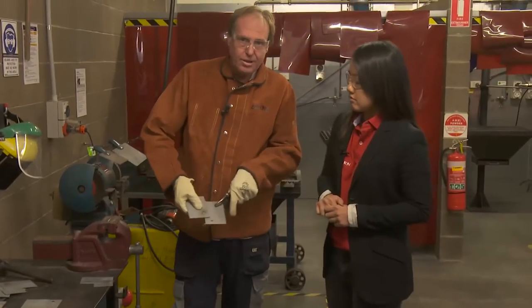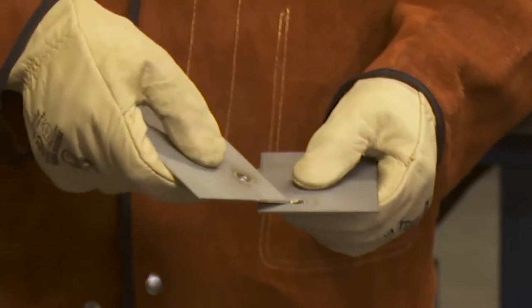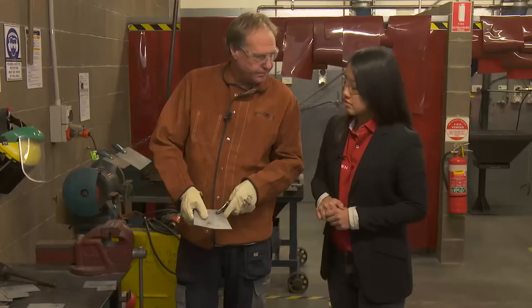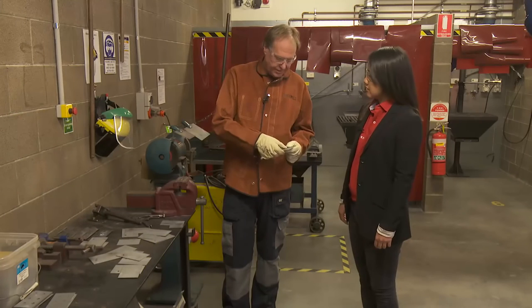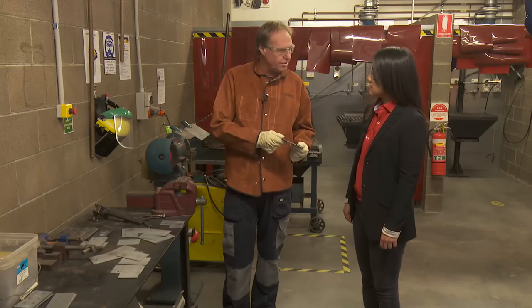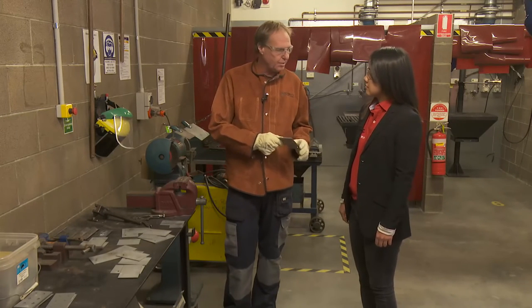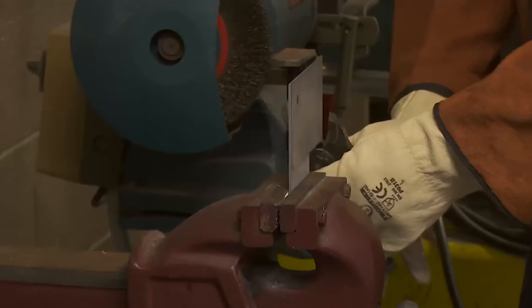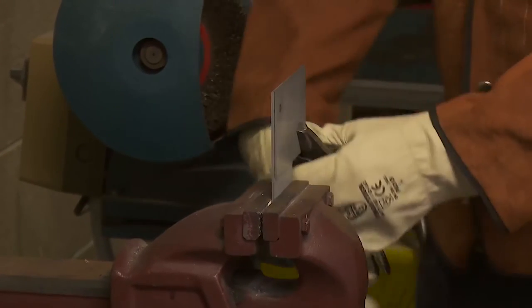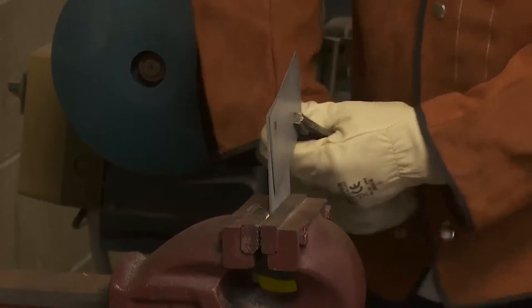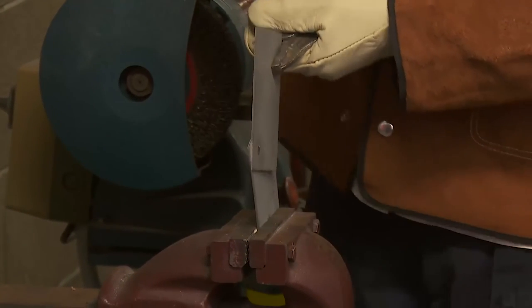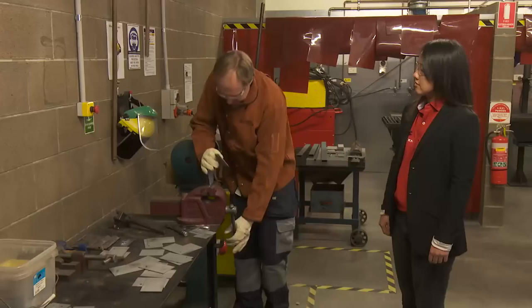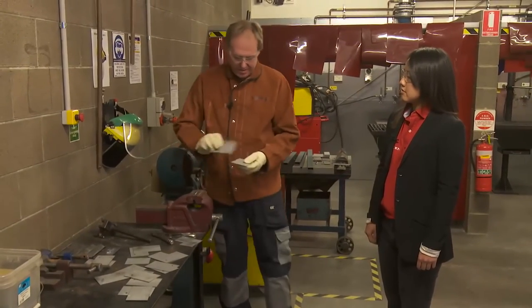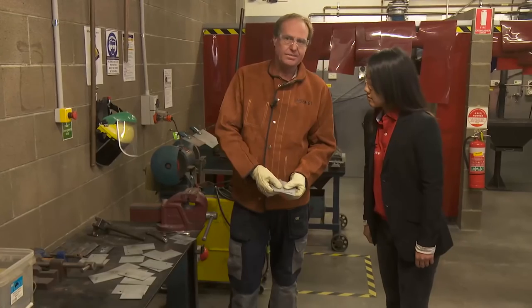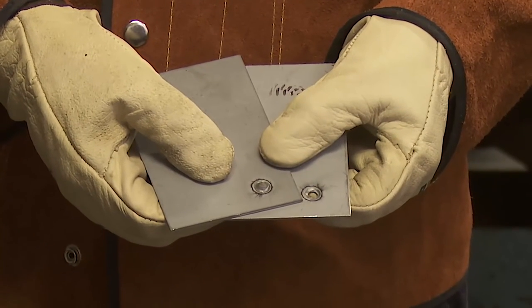Turned out to be a good plug because of the fact it's pulled out a nugget out of the base plate. And that's how a plug weld should test up. Resistance spot welds. They look nice and neat, look like they're going to do the job. We'll put that in the vise and we'll do a destructive test on that as well. These should pull a nugget out like the MIG plug pulled out as well. And as you can see, we've got tear out that we need to hold the structure together.